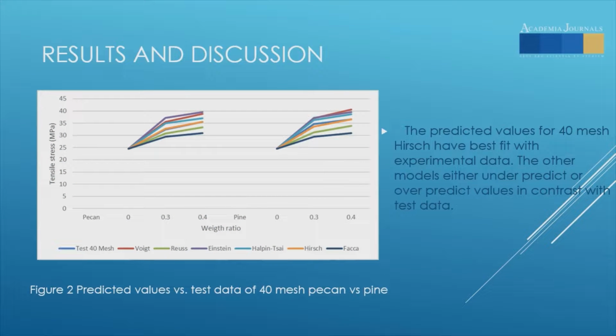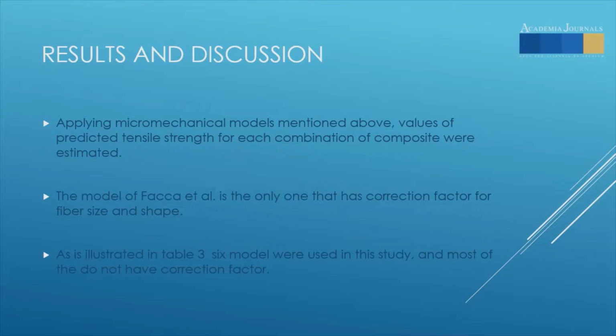For 40 mesh, the results show that at 30 and 40% for pecan the values are all over the place. However, the Hirsch model is the one that best suits pecan as well as pine wood. That's very interesting for this particular model, because the 60 mesh does not have this same behavior. So finally, we can say in these results that most of the micromechanical models are either under predicting or over predicting the tensile response, which is a factor in not being able to fit the experimental data better.